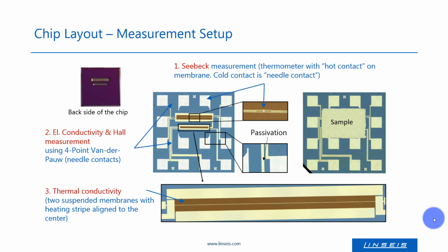The membranes are mainly used for the thermal transport and Seebeck measurements, and the needle contacts for the Hall and resistivity measurements. The front side of the chip is mostly covered with an insulating layer. Thus, the sample is not forming a short circuit with the on-chip heaters. The empty chip can be seen on the left side and the covered chip, ready to measure, on the right side.